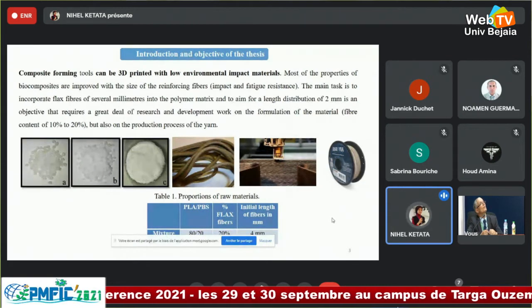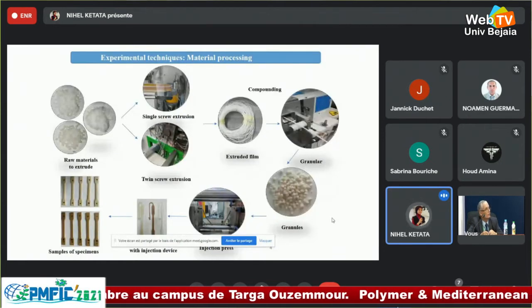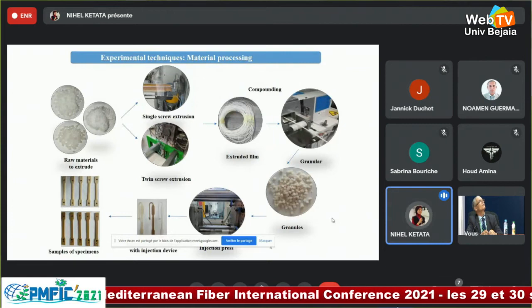So the main work is concentrated on 3D printing materials with low environmental impact using the FDM process. It is a biocomposite from a mixture of 20% of PBS and 80% of PLA reinforced with flax fibers at about 20%. We can manufacture the test specimens using two extrusion methods to compare them in terms of mechanical results and, most importantly, fiber distribution.